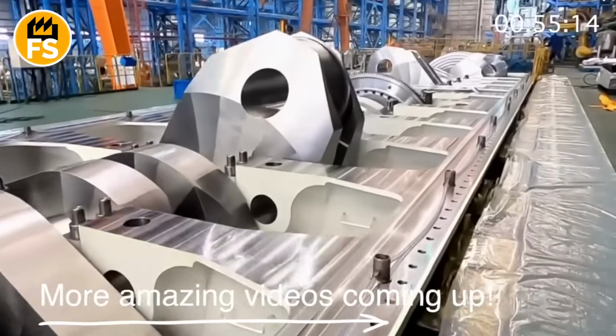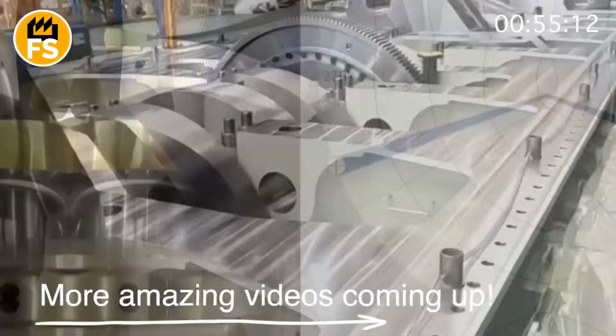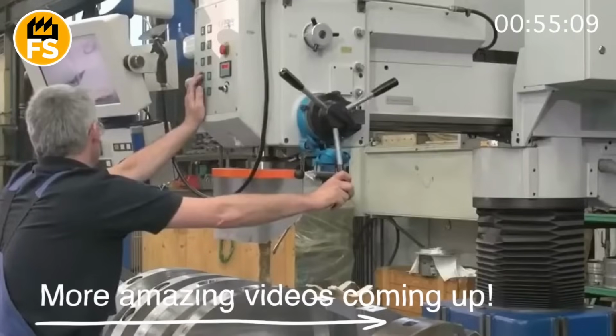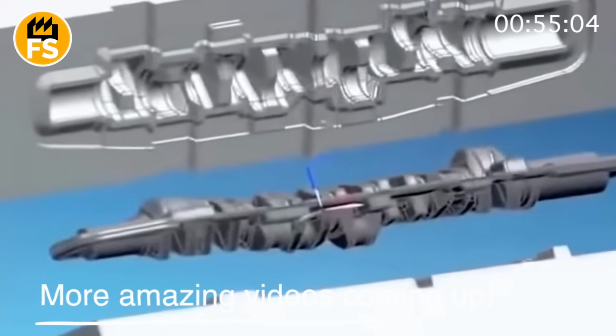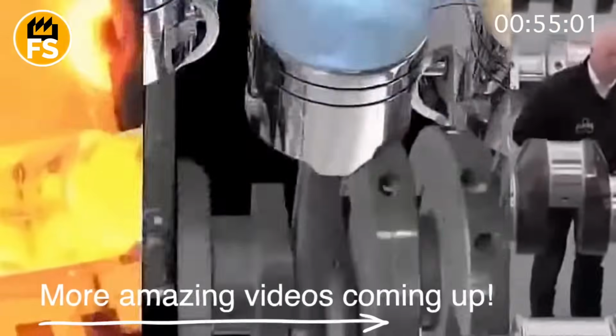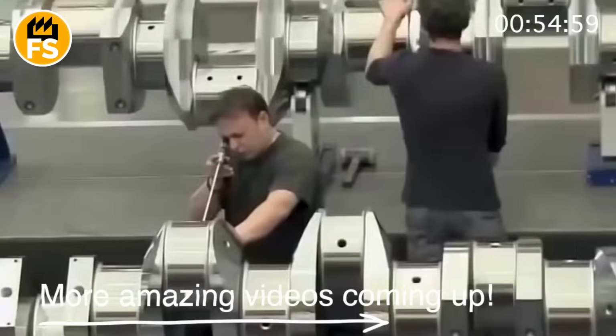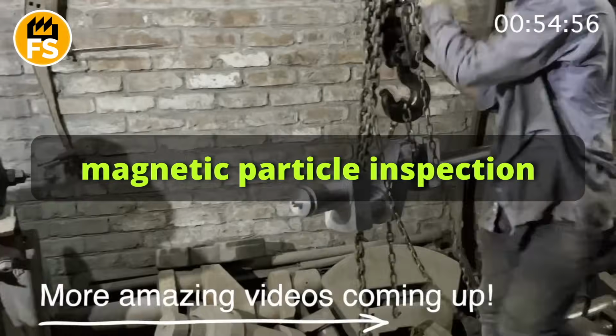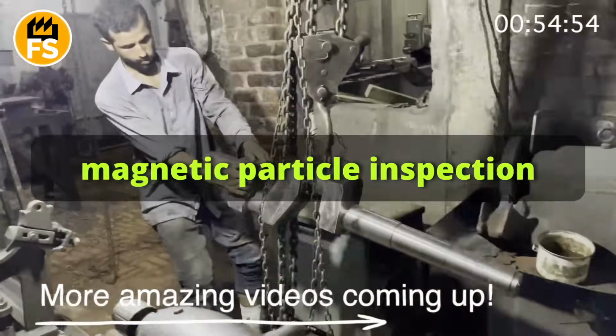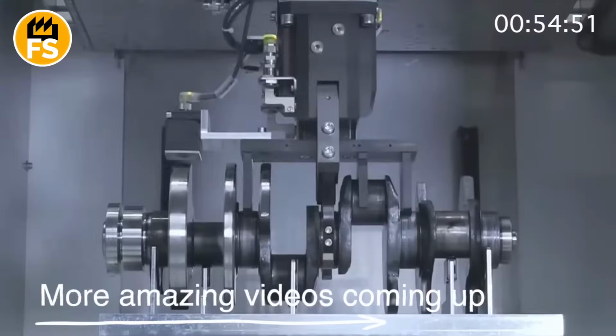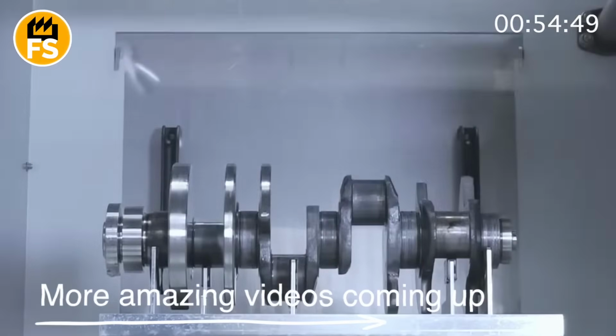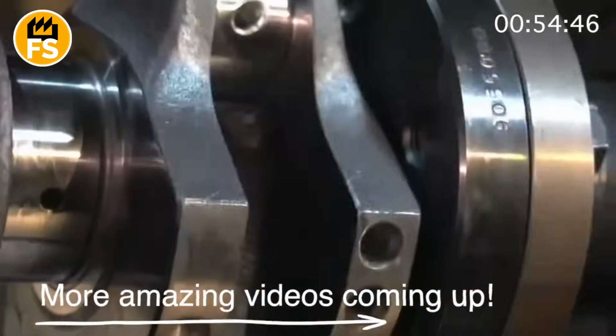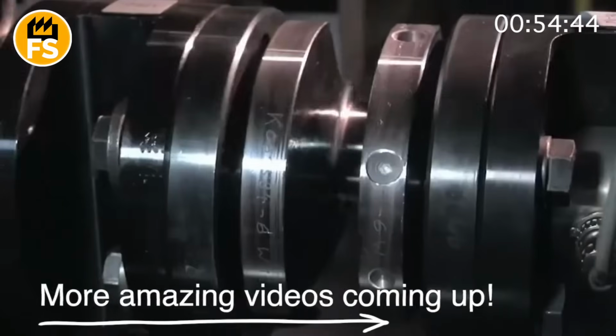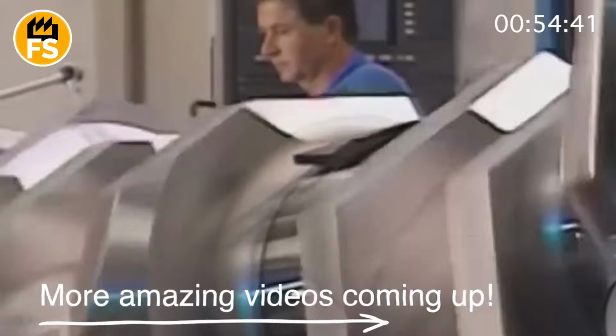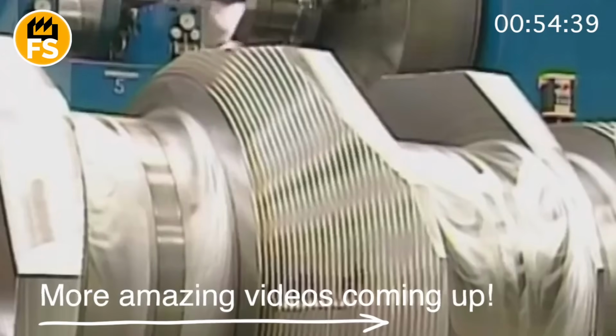Then, ultrasonic scanners are used, which penetrate deep into the metal and detect internal defects, voids, inclusions, stresses in the structure. The crankshaft is wrapped with special sensors, and a computer system reads the signals and creates a 3D map of its internal structure. Next, magnetic particle inspection. This method allows finding the smallest surface cracks that may be invisible to the naked eye. The crankshaft surface is coated with a magnetic powder, and under the influence of a magnetic field, the powder particles gather at the defect sites, clearly highlighting them.